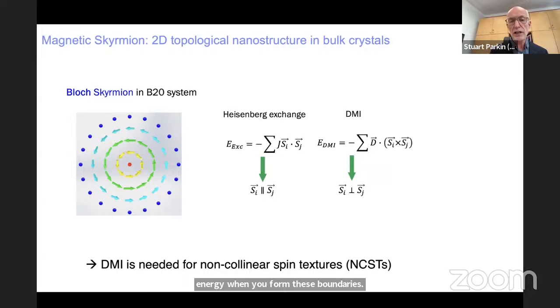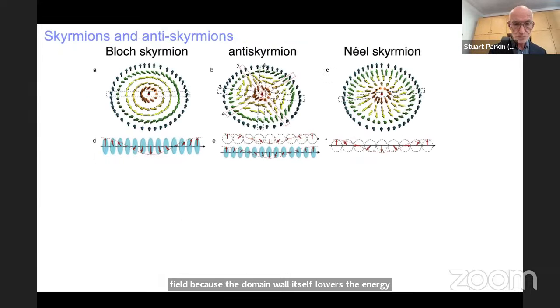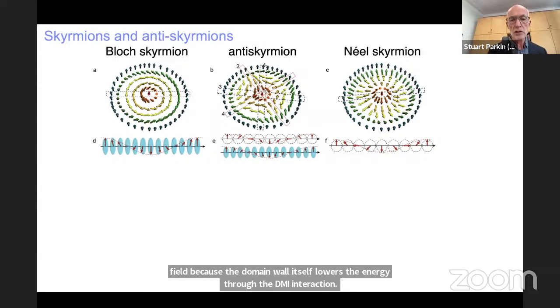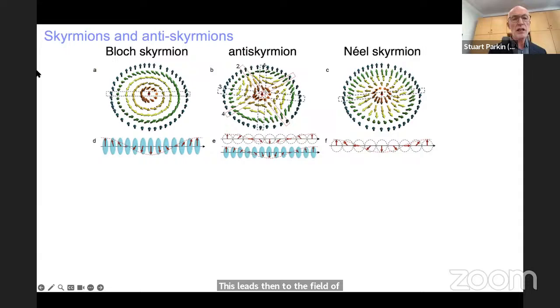So in these systems, you can find these skyrmions in some range of temperature and field, because the domain wall itself lowers the energy through the DMI interaction. This leads then to the field of non-collinear spin textures. On the left-hand side is the object I just showed you, the Bloch skyrmion, and it has a close partner, the Néel skyrmion, shown on the right-hand side, which is the two-dimensional equivalent of the one-dimensional domain wall introduced two foils ago. In this case, the magnetization rotates from up on the periphery to down in the middle by rotating with the moments in the wall being along the radius rather than along the circumference, as in the Bloch skyrmion.